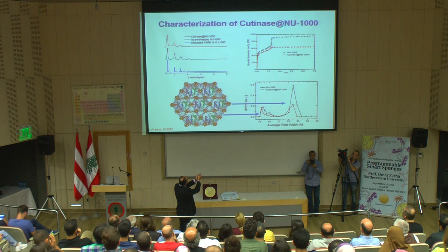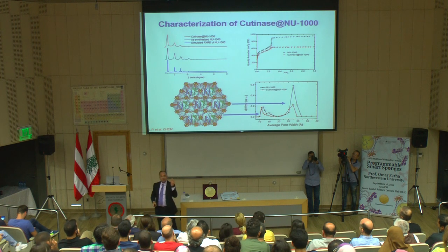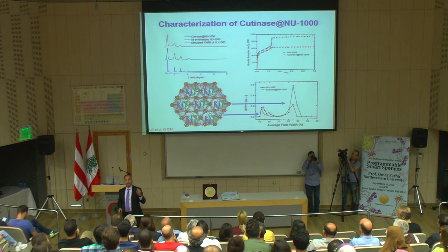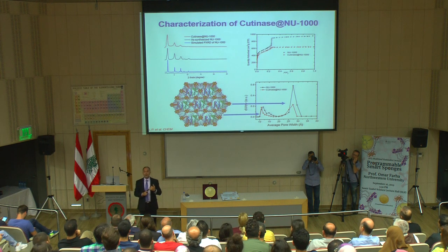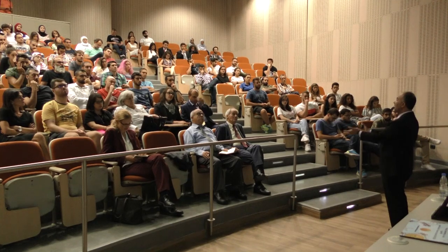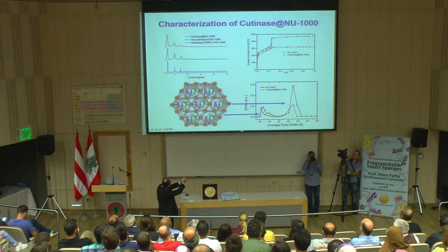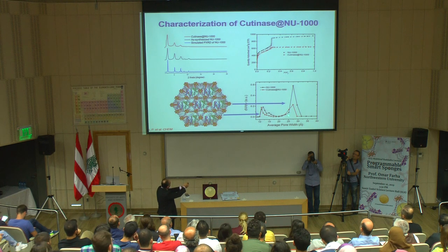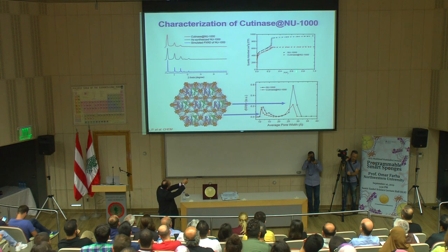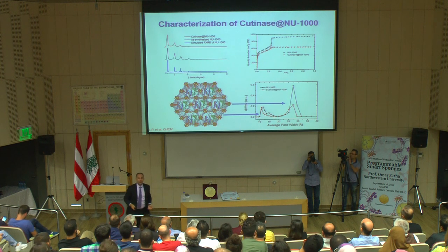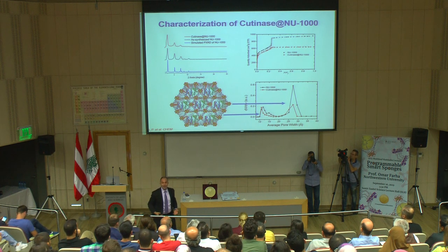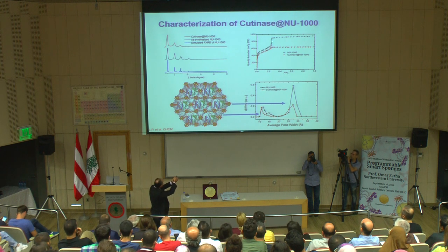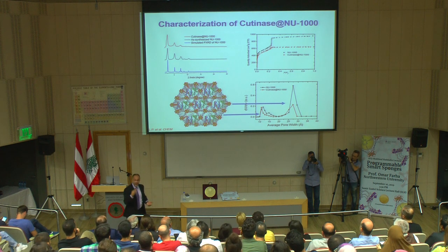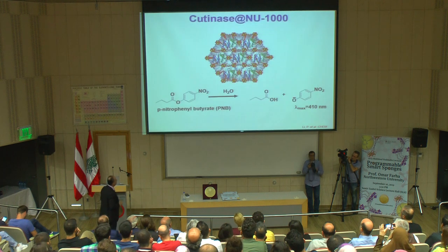Look, from this nitrogen isotherm, we could extract three pieces of information: one, the pore volume, how much porosity inside; the surface area; and the pore size distribution. So from that plot, we extracted this pore size spectra. But look when we put the enzyme. Nothing happened to the small channel, and all the reduction came from the large channel. That means that's where the enzyme is really residing. And you could see that step reduced drastically because that's the signature of the hexagon.